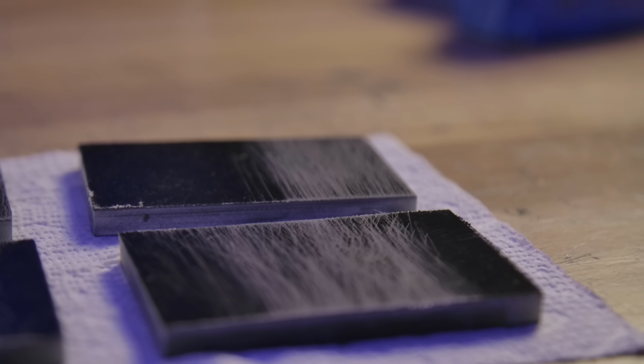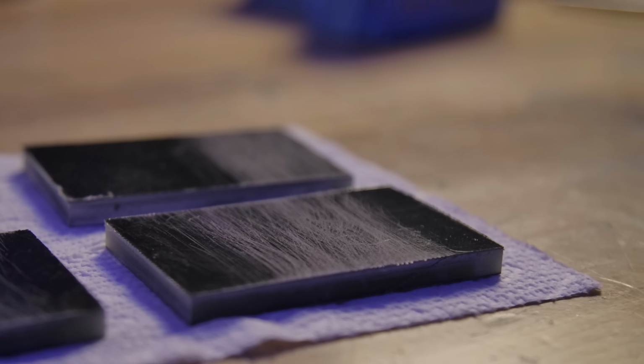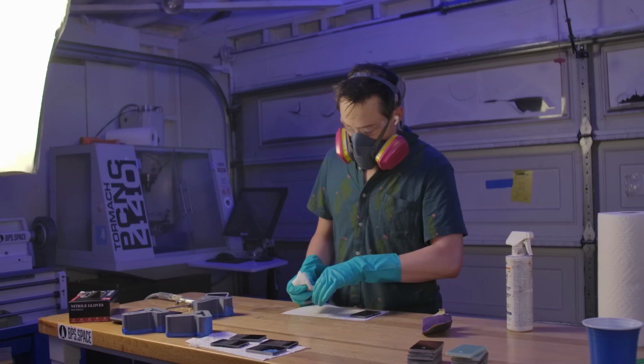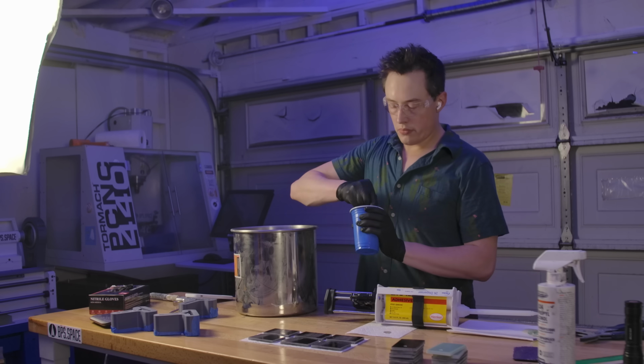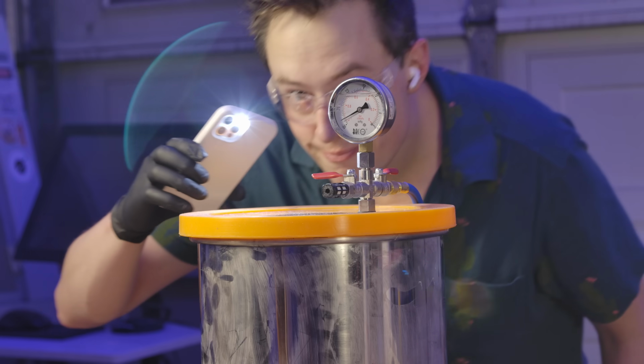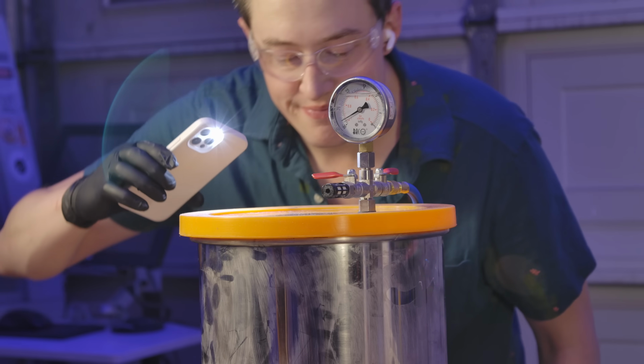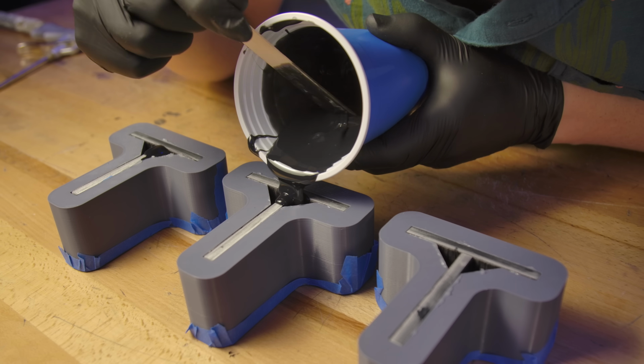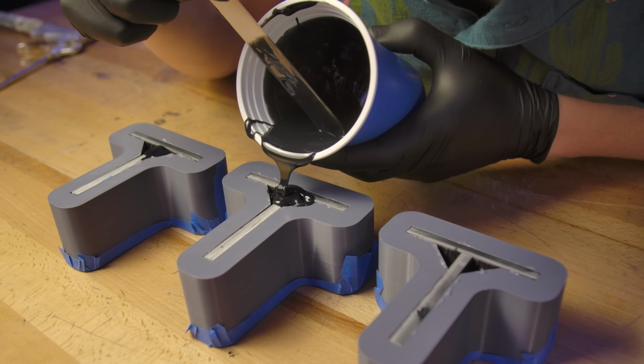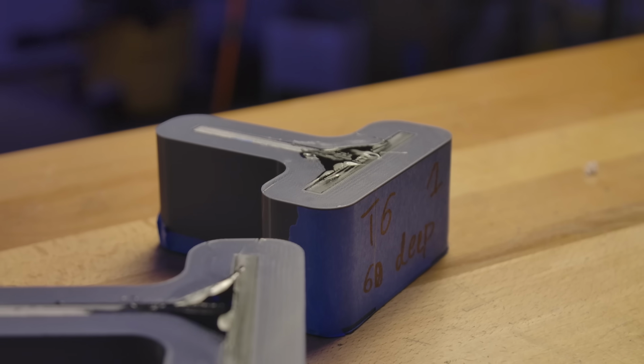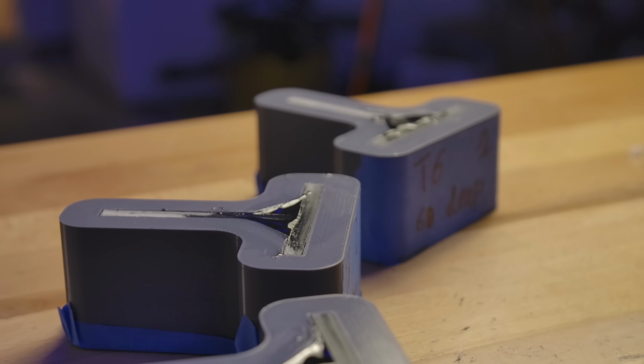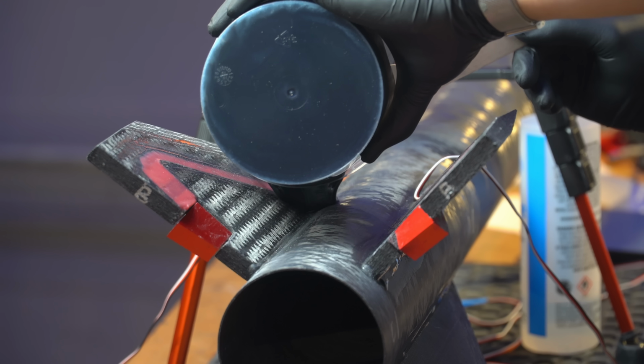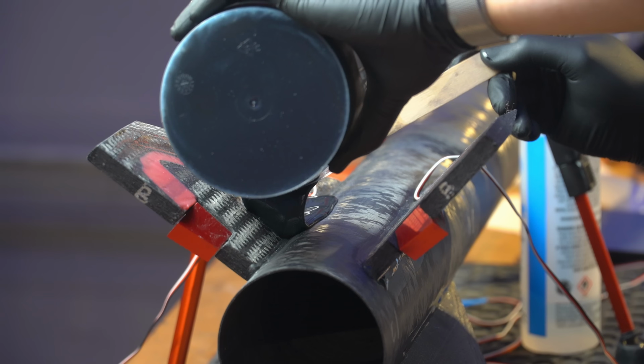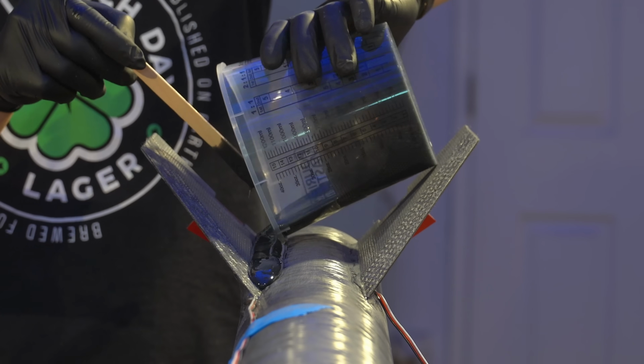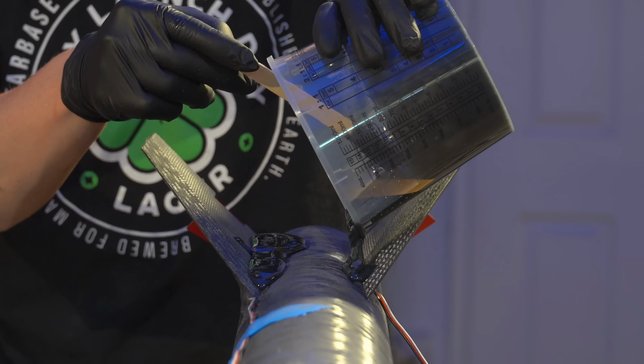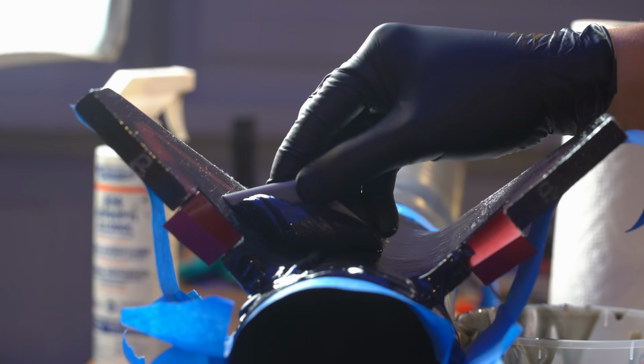I kept the sanding direction mostly consistent, aiming to create deep, straight grooves, then I wiped each surface off with IPA to clean it. I then mixed up another batch of Loctite E120HP with a bit of black dye, and vacuum degassed in the mix cup before pouring it into the mold. I was burnt out by this point, so I skipped the step of re-degassing the epoxy while it was in the mold. This is another inconsistency, and if these results perform well enough, I figured I could rerun them with more degassing. This is also more accurate to the way I'll be bonding fins onto my rockets. These fillets will be big enough that it'll be hard to degas the epoxy once it's on the surface, but all of this assumes I ever find a good solution here.